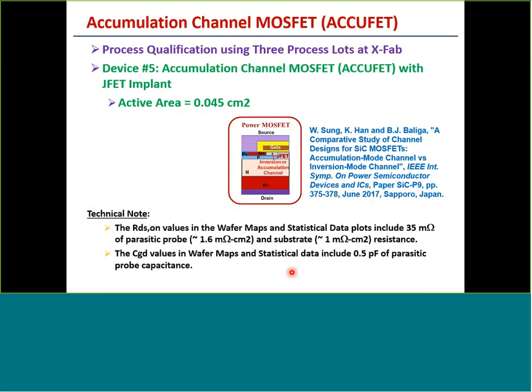I'm now going to turn to the qualification of the MOSFET. Here, I'll focus mainly on the AccuFET because it has better RDS on, and these devices have an active area of 0.045 centimeters squared. I want to point out that when we measure these devices on a probe station, we experience a parasitic resistance of about 35 milliohms, which translates to about 1.6 milliohm centimeters squared as a specific resistance. In addition, of course, the substrate itself contributes about 1 milliohm centimeters squared. In addition, there is a small parasitic capacitance of 0.5 pF in our CGD measurements.